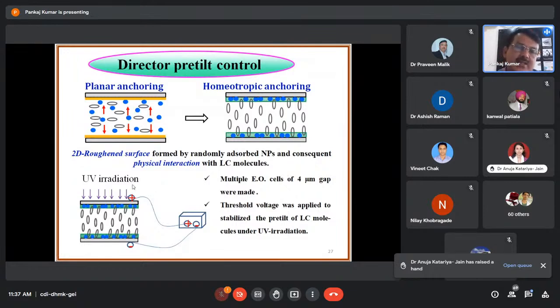And in that case, if we apply 2 volts or 1.5 volts, then 2.5 volts or 2 volts, with the help of this applied voltage, all the liquid crystal molecules will deflect in some particular direction. And at that time, we can cure these cells so that the pre-tilt angle can be maintained. So the threshold voltage was applied to stabilize the pre-tilt of liquid crystal molecules under UV radiation.